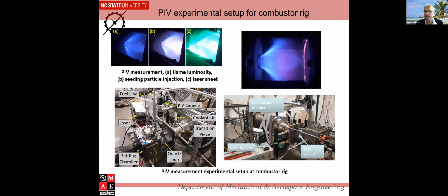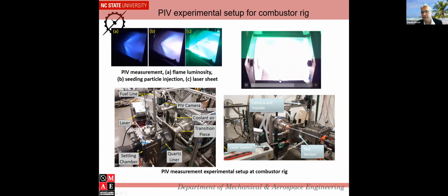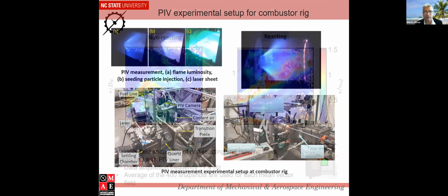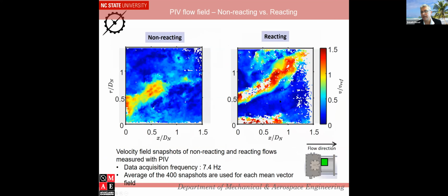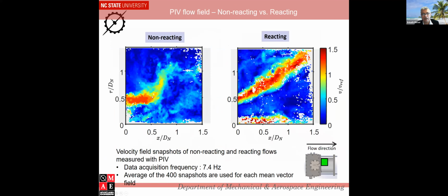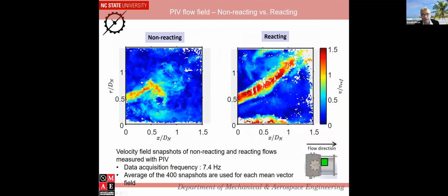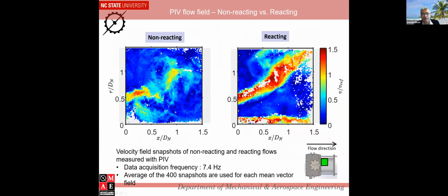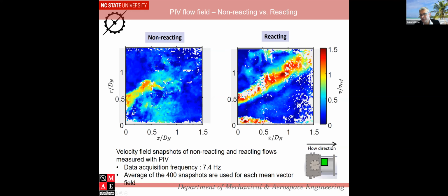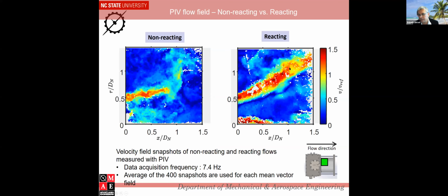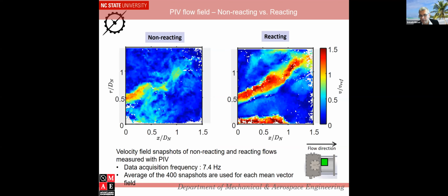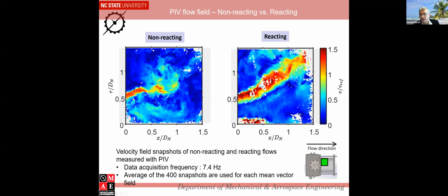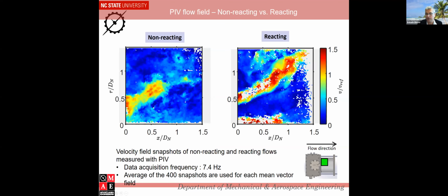We use different kinds of fuel. This shows you our test rig and experiments. And you can see the flame burning fully with the video camera, and the laser pulses are going right now. And then we take the images, and this is how the non-reacting versus reacting looks. In the non-reacting case, you can clearly see that the flow is not fully structured. It comes out and it kind of flakes off. It never comes near the wall. Whereas when you see reacting, reacting makes the flow much more structured and coherent. And you actually see the pilot flame also here, and you can see the reaction here. This is the raw images of the reacting versus non-reacting flame, right?